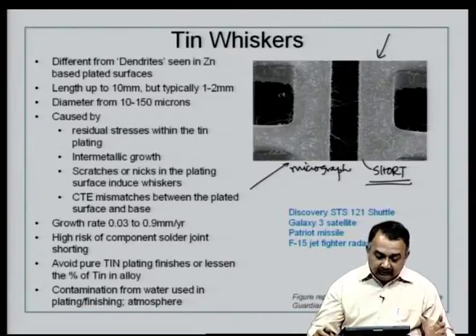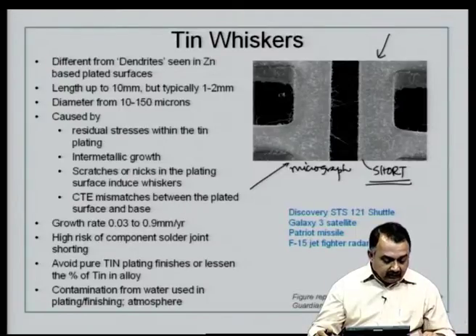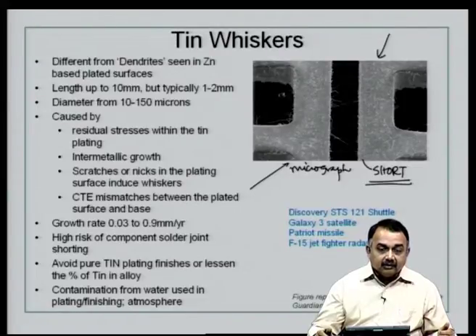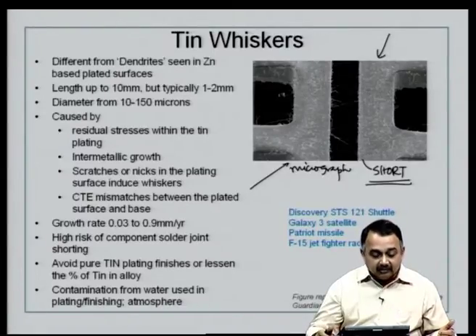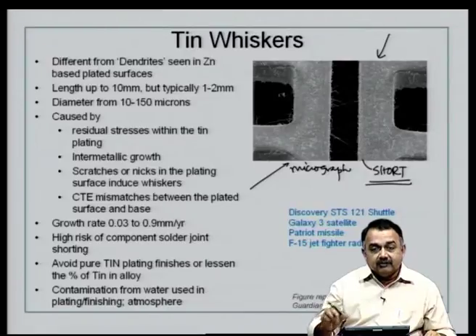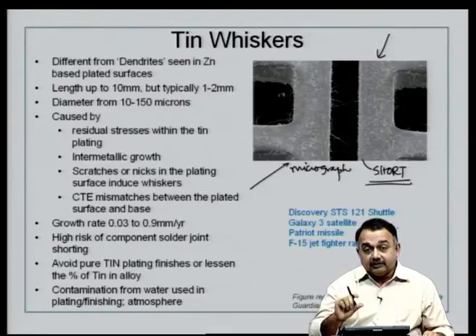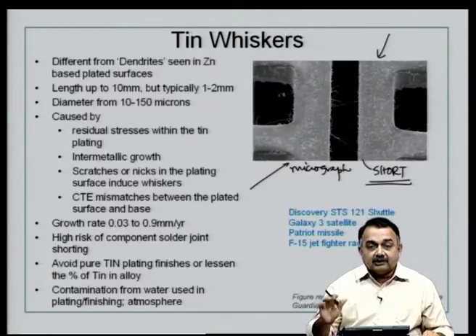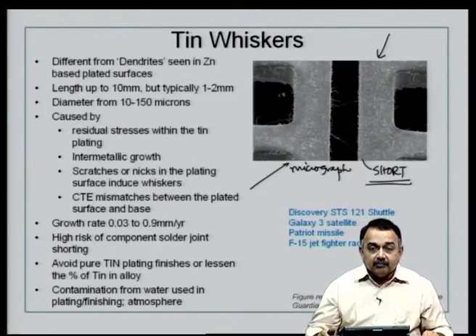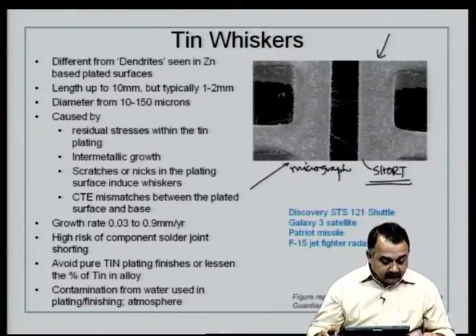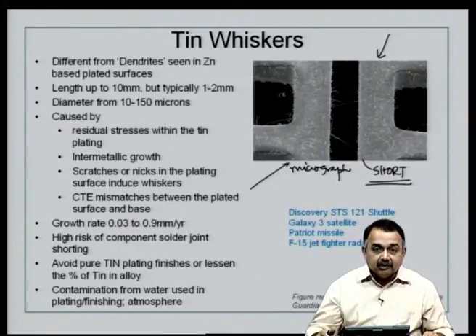But if we use a large percentage of tin, you are going to end up with a lot of defects like this. Typically the problem of tin whiskers was in 2005, when the Millstone nuclear generating plant in Connecticut, in USA, observed a shutdown of its plant because a steam pressure line short circuited. This was because of a defect in one of the PCBs in the electronics that had been used to control these steam pressure units. So, that is a major setback, and they had to replace these with better PCBs.